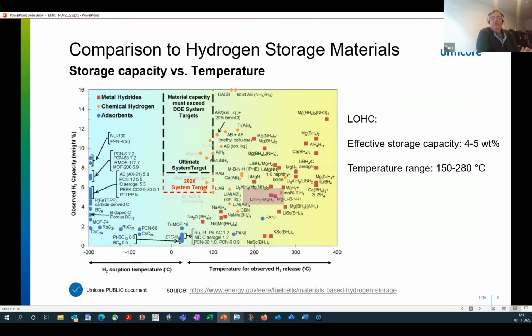If we compare to hydrogen storage materials, of which we had a nice presentation just before, the effective hydrogen storage capacity in an LOHC is 4 to 5 weight%. And the temperature you need to release the hydrogen is typically between 150 to 280 degrees, sometimes a little bit higher, with the pyridines a little bit lower. So we are operating in this box that is in the graph. So we are comparable to a lot of hydrides, but temperature will always be an issue.